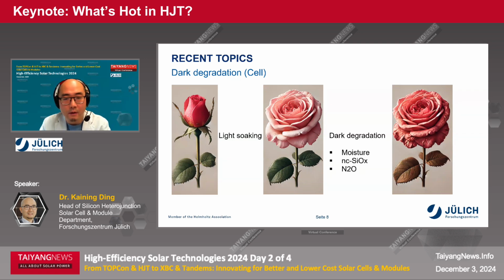But most recently, there have been some reports about using N2O as an oxygen source for the nanocrystalline silicon growth instead of CO2, and the dark degradation issue seems to be controlled by changing this step. This indicates somehow that the dark degradation might also be related to the carbon that is being introduced, in a small fraction, into the material while growing the nanocrystalline silicon oxide. So it's not really understood yet what is going on there with the dark degradation.